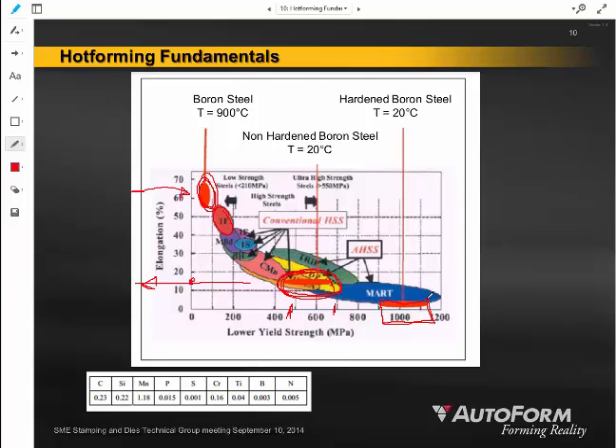If you take 1008 1010 steel and heat it up to 900 degrees Celsius and then form it and then cool it, that material is going to come back to you in an annealed state, a softened state, and that material is going to be less strong and less structurally sound than it was when it came off of the cold rolling mill. That material would have very much a hot rolled quality to it, and it would lose a lot of the strength and characteristics that we like in our mild steels.